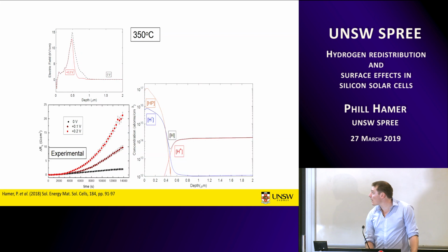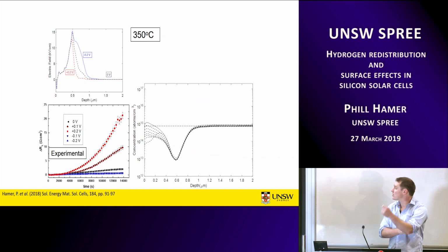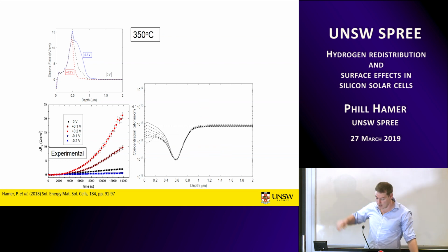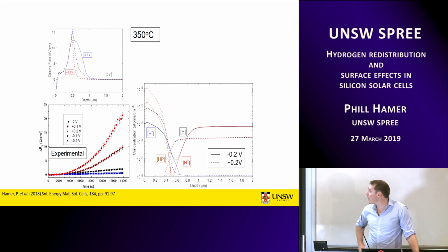as shown here. If we then apply a reverse bias, you would expect a greater electric field in that p-type region, and hence H+ to be repelled away and us to have less contact resistance increase. And rather fortunately for the purpose of this presentation, that's exactly what we see. If we apply a high enough reverse bias, we can almost completely suppress this contact resistance increase, and we have no effective change in series resistance. And again, you can see here, there's now a very steep gradient for H+ approaching that inflection point, in comparison with hydrogen with a positive charge applied.